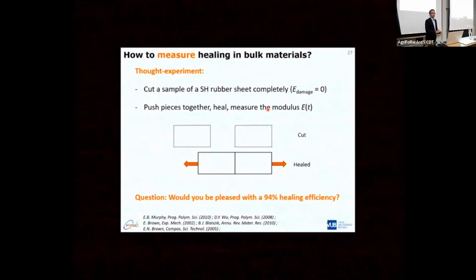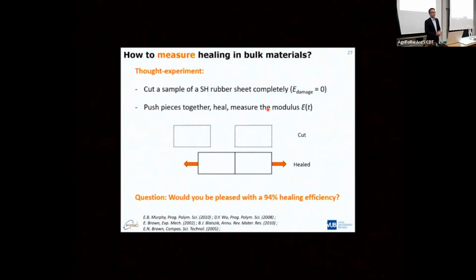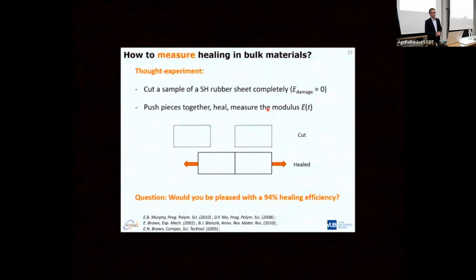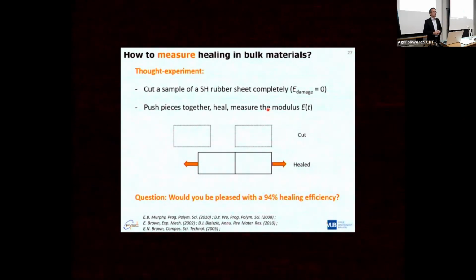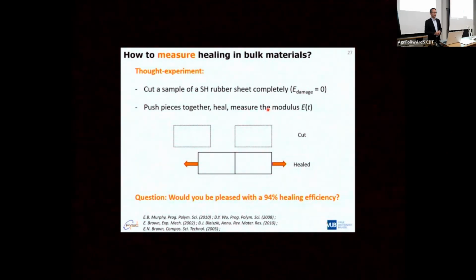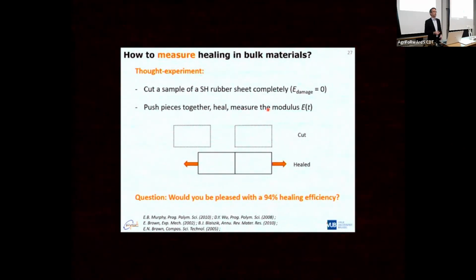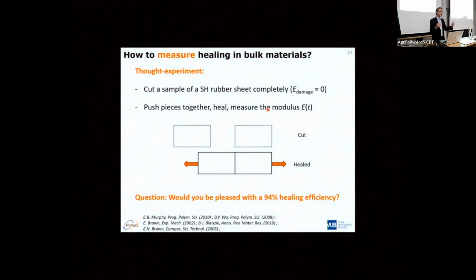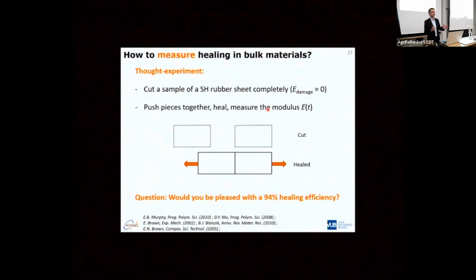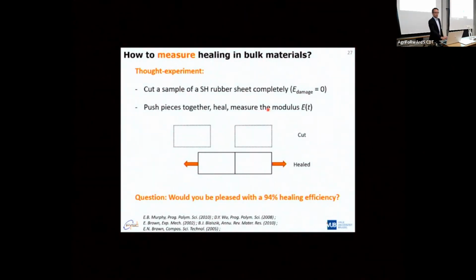Now, if you consider measuring that healing, you could consider the following situation. You take a sample, a small testing bar, you cut it in two, put it back together again, and heal it under certain conditions, with or without pressure, with or without temperature, and so on. And then we measure the modulus of that bar, and we compare it to the original modulus of the material.